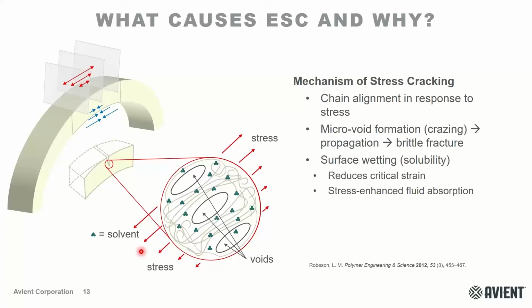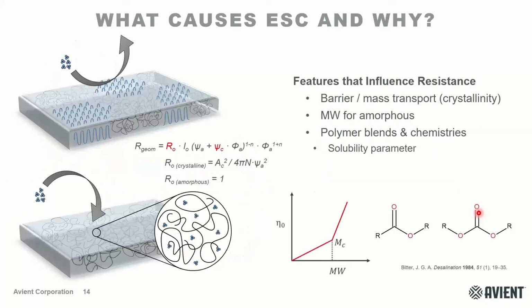And then the last thing to bring up here too is that there's an observed phenomenon called stress-enhanced fluid absorption. So where your part is under the highest amount of stress, it'll tend to uptake the most solvent. And this is a function of just reducing its free energy. So it wants to localize that solvent to the area of stress so that the material itself can relax in response to that stress. So that's a little bit of a mechanism of how environmental stress cracking proceeds.